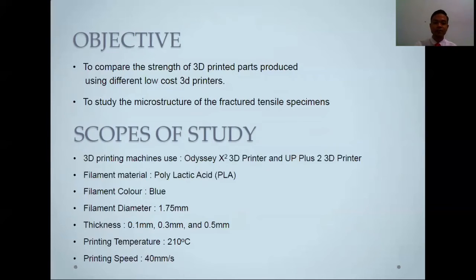Next is the scope of study that contains a few things. Firstly is the brand. The brands of 3D printing machine used are the Odyssey X2 3D printer and the UP Plus 2 3D printer. For the filament, the material is polylactic acid PLA that has 1.75 mm diameter and is blue in color. Then the scope during the printing process: the layer thickness is 0.1 mm, 0.3 mm and 0.5 mm. Printing temperature is 210 degrees Celsius and printing speed is 40 mm per second.